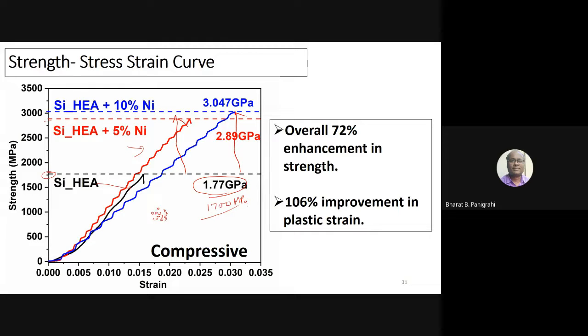This nanocrystalline structure has a very high strength and very high hardness. And by adding nickel, we are providing a softer matrix. So there is a combination of a high strength phase and a soft matrix, and that has led to a massive combination for designing a material with ultra high strength. You can see a strength of 3 gigapascal. You will never find such a high strength in an alloy. It's very difficult to find. What I am trying to say is such alloys have extremely huge application scope where you can design a high strength material.